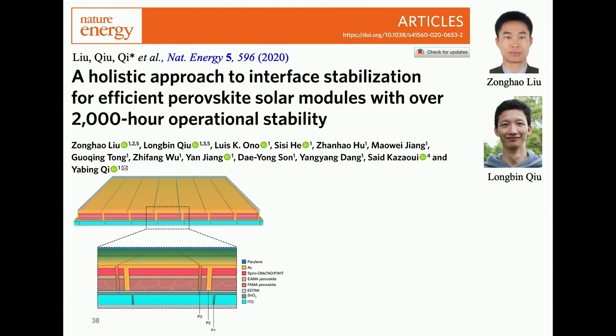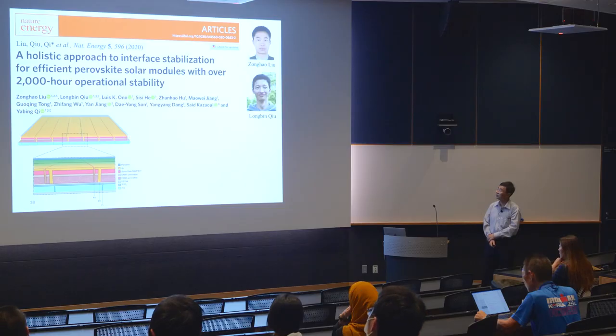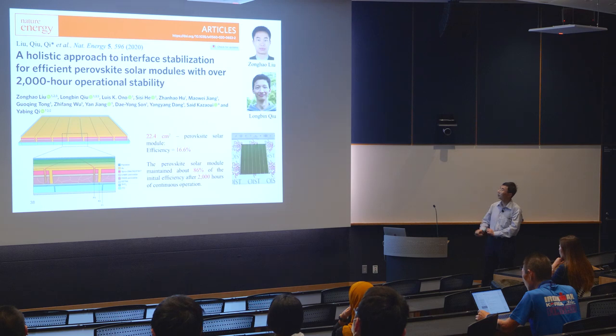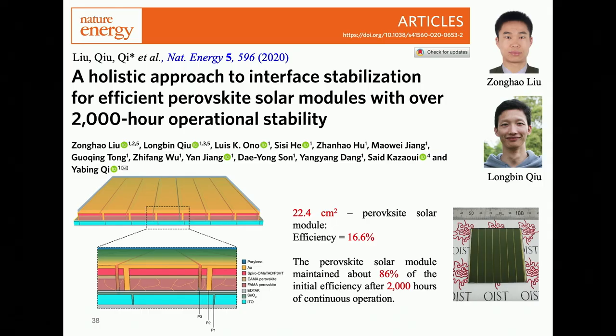For each of the interfaces and surfaces in the perovskite solar module structure, they applied a certain strategy to optimize. And as a result, we could obtain the perovskite solar module on an area of 22.4 centimeter square, not only showing a high efficiency of 16.6%, but also demonstrating stable operation for 2,000 hours.